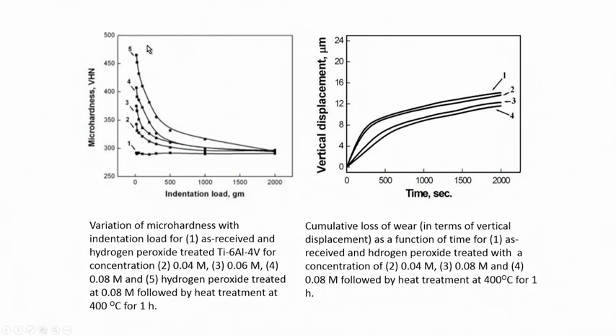Accordingly, the microhardness also changes because of formation of the anodized film. You will find an improvement in hardness, and the depth of the hardening was around 10 to 15 micron. That percentage of oxides, or the thickness of the oxide scale, was enough to confer good wear resistance property on the surface.